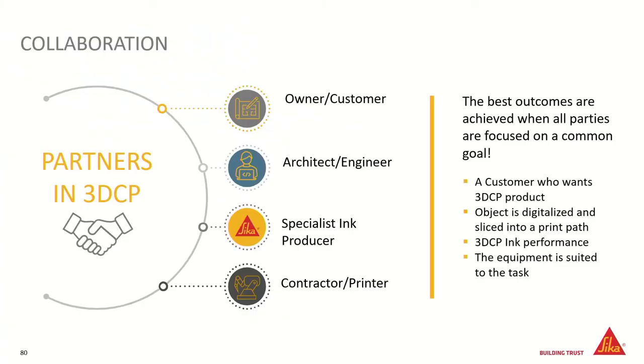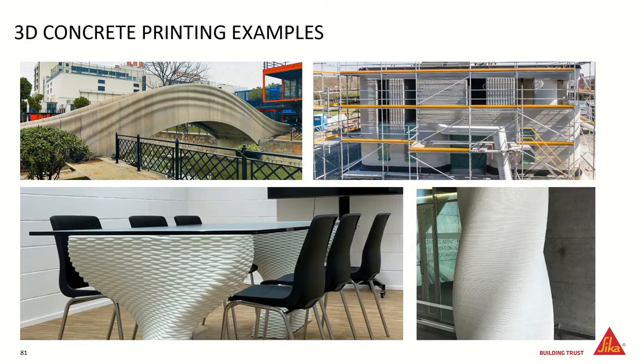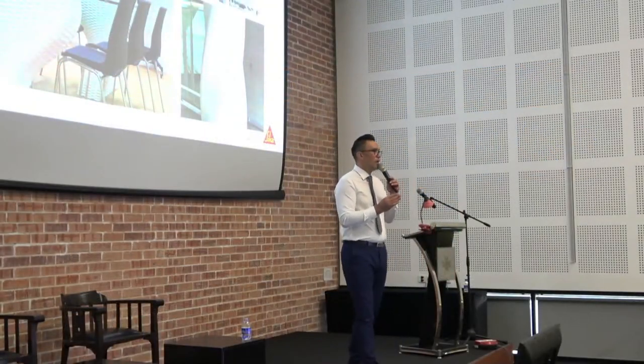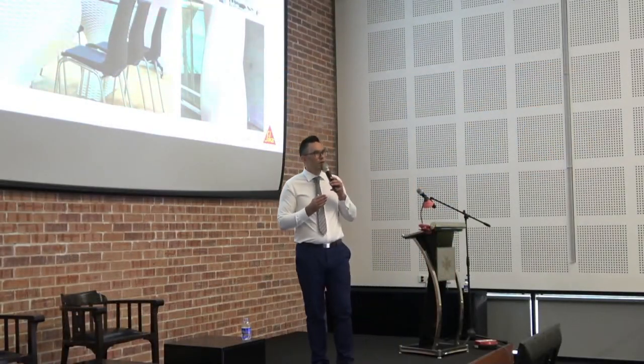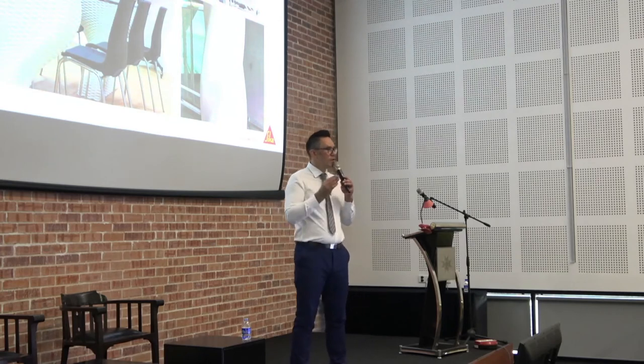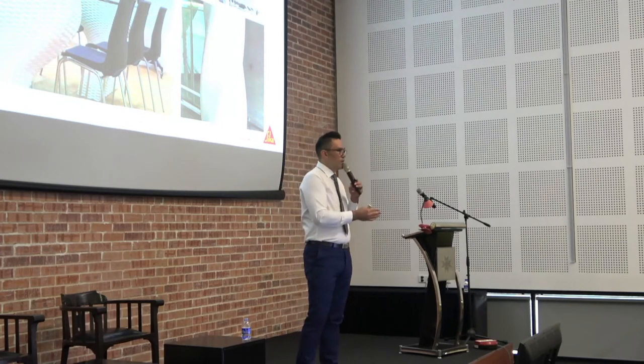So if you haven't seen, there's a couple of pictures in here which will show you what's achievable. So we can print bridges now. This is the first house that's printed by a company called Perry. Again, it's printed, but they printed the shell. And then they cast regular structural concrete inside two lines of printed material. And that's generally how houses are being printed at the moment. The shell gets printed, and then the structural element inside.